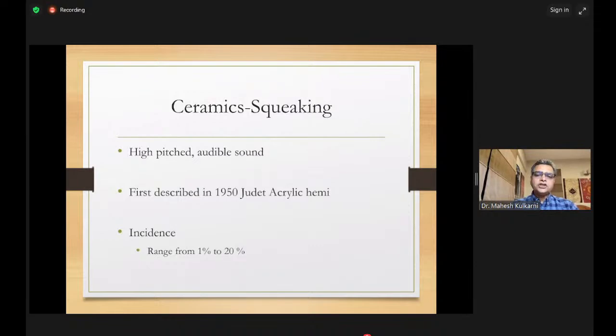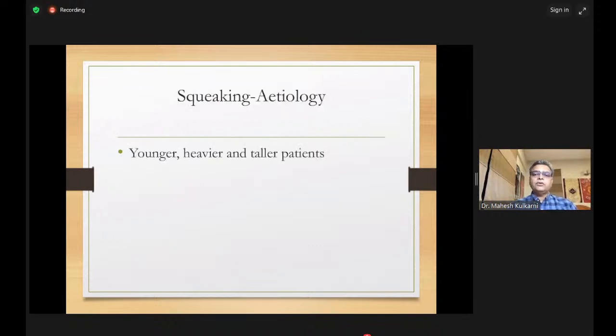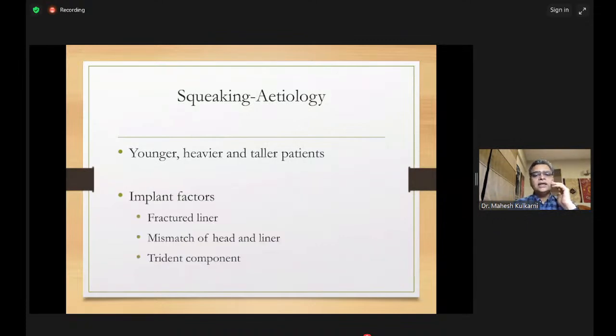Squeaking is a high-pitched audible sound, first described in 1950 by Judet with his acrylic hemiarthroplasty, an acrylic hip replacement. Incidence ranges from 1 to 20%. When do we see squeaking? You will see it in younger, heavier, and taller patients, and if you have a fractured liner or an impending fracture, or if there is a mismatch of a head and